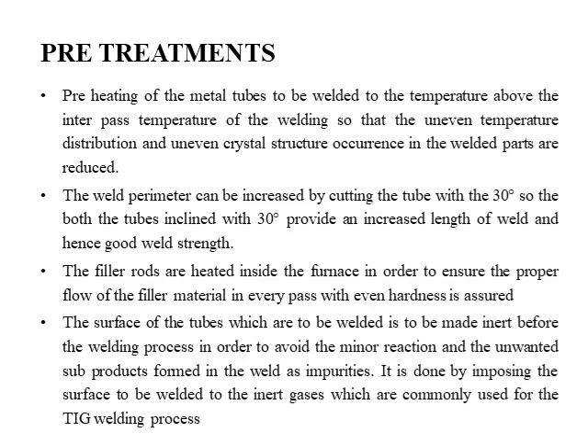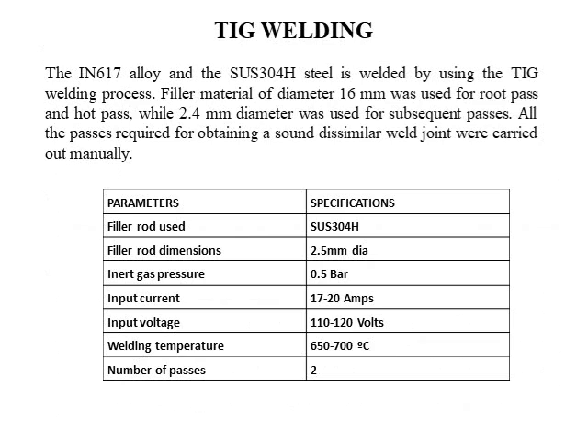The surfaces of the tubes to be welded are made inert before the welding process by inert gases. The inert gas generally used in the TIG welding process, and the gas used here is argon. The filler rod used in TIG welding is SUS 304H. We can also use Inconel 617 alloy as a filler material, but due to inadequate filler rod availability, we used SUS 304H. The filler rod dimension is 2.5 diameter, gas pressure is 0.5, and 17 to 20 ampere current is supplied. The input voltage is 110 to 120 during the welding pass. The welding temperature is 650 to 700 degrees Celsius. We used 2 passes.